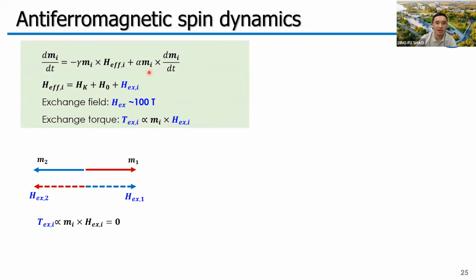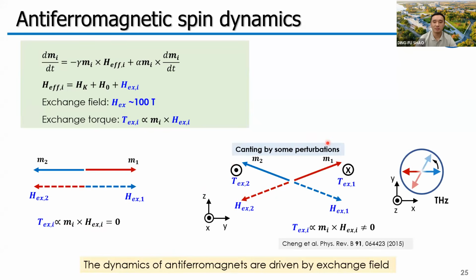Here is the LLG equation of one sublattice of collinear antiferromagnets. Here we have an effective field, which includes the anisotropic field, the external field and the exchange field. The exchange field is due to the exchange coupling of the two moments on the two sublattices, and it can generate an exchange torque, M cross exchange field. Obviously, if the two moments are perfectly anti-parallel to each other, this exchange torque must be zero. But if we can find some perturbation to generate a canting, this cross product will not be zero anymore, so that we can have staggered exchange torques for these two magnetic sublattices.